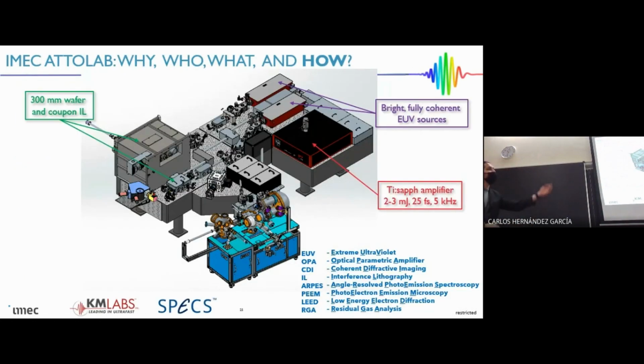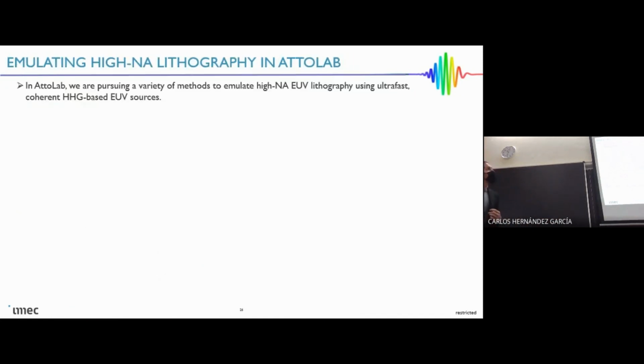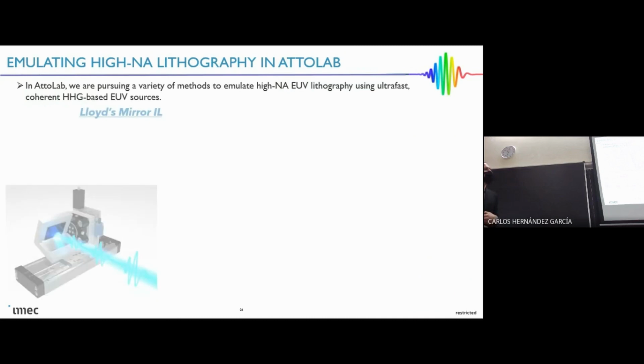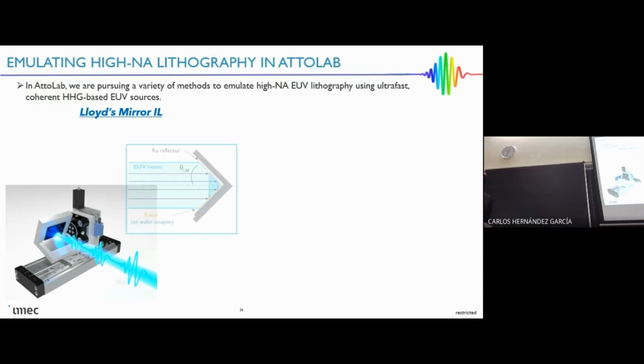The next thing I want to talk about then is going into the interference lithography studies in AttoLab. And we have 2 ways of doing this. One is in a big chamber, and then we have a smaller chamber for smaller samples. For these 2 methods that we deploy, one is referred to as a Lloyd's mirror device. This is actually a very, very simple device. It takes a reflector and pushes it up against a photoresist, and then using a partial reflection of the EUV beam, it creates an interference pattern on the photoresist.